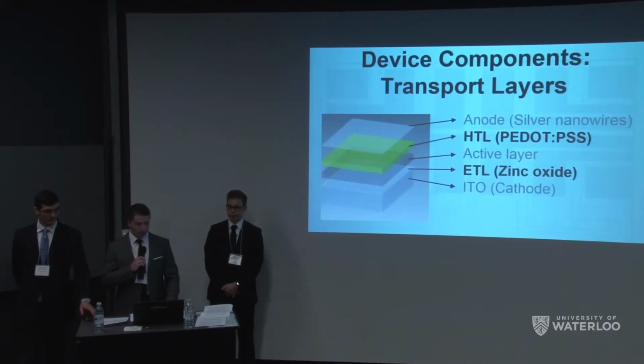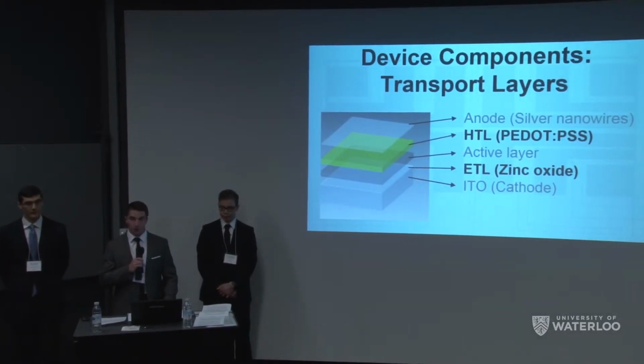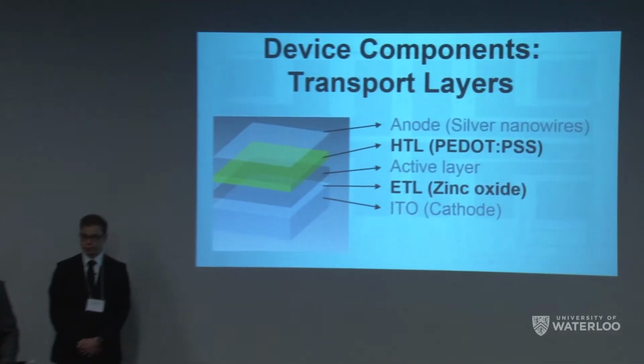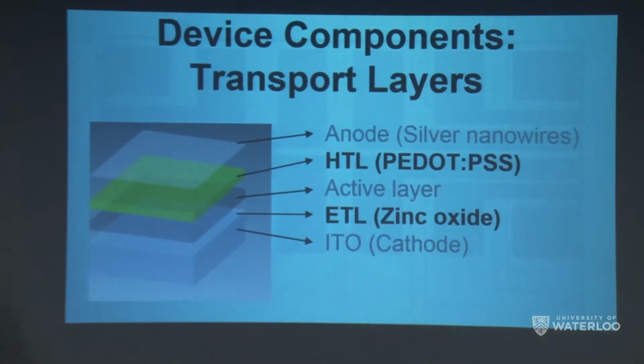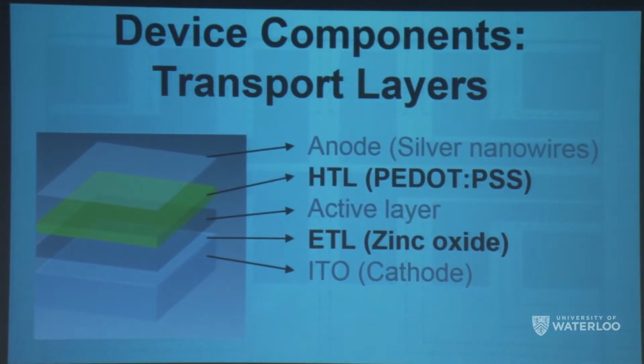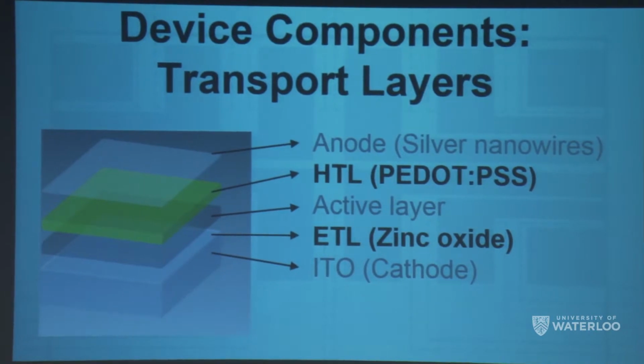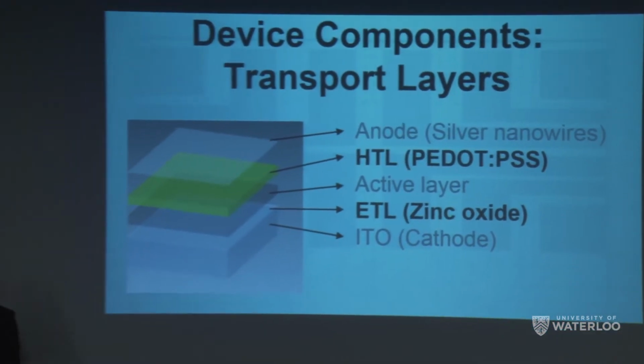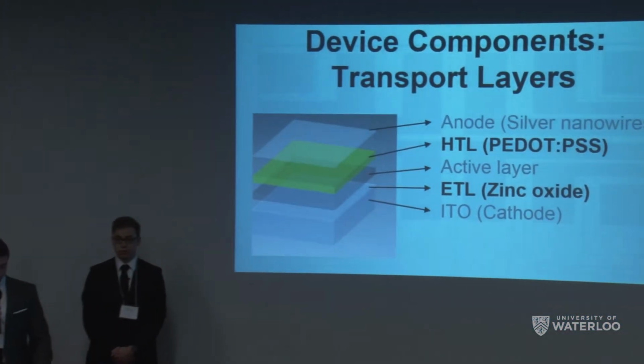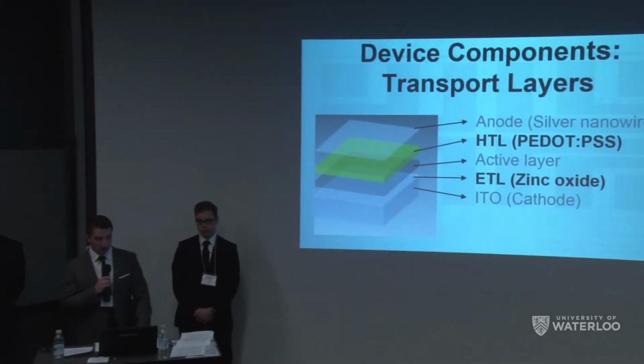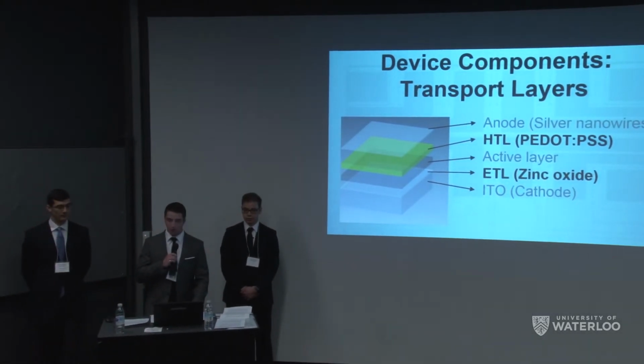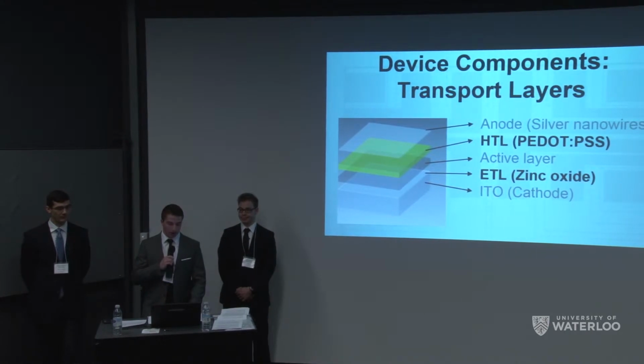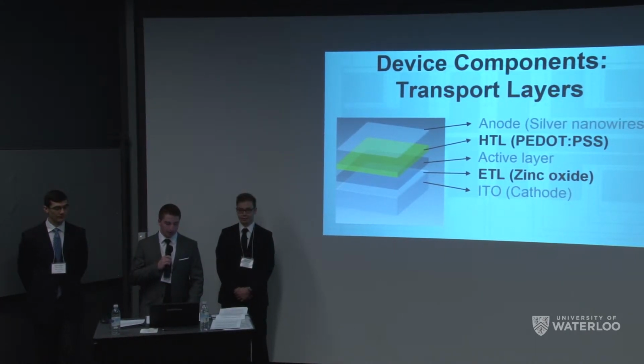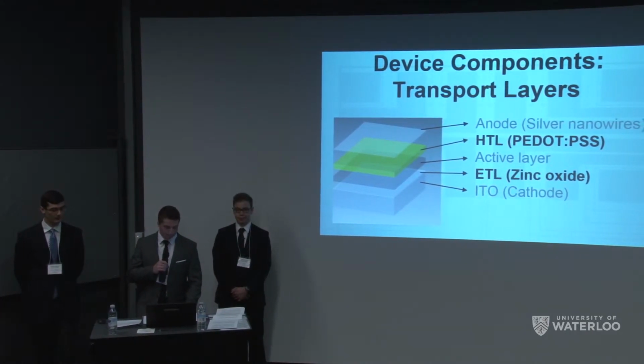For our transport layers, we chose to use zinc oxide as an electron transport layer, and a conductive polymer called PEDOT:PSS as a hole transport layer. Both of these materials form very thin films when solution processed and can be deposited using spin coating methods. Zinc oxide and PEDOT:PSS were both chosen as carrier transport layers because they are almost entirely optically transparent and provide the necessary electrical contact to interface with the electrodes and active layer.